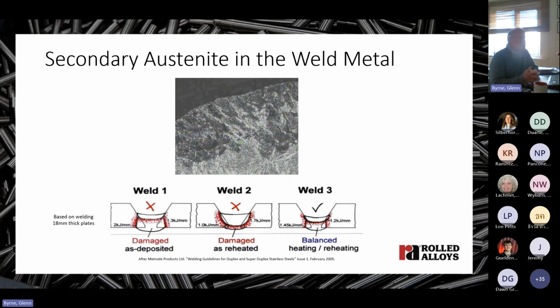Thermodynamic work has in fact confirmed that secondary austenite formed below 1050 centigrade is lean in chromium and particularly nitrogen. So it has a lower PREN than primary austenite, and hence the corrosion resistance is poorer than primary austenite. And you can see in this micrograph here, these stringers of the white phase are primary austenite, and they're retained in the structure. And these darker areas are where the secondary austenite has corroded in a ferric chloride test of a weld.